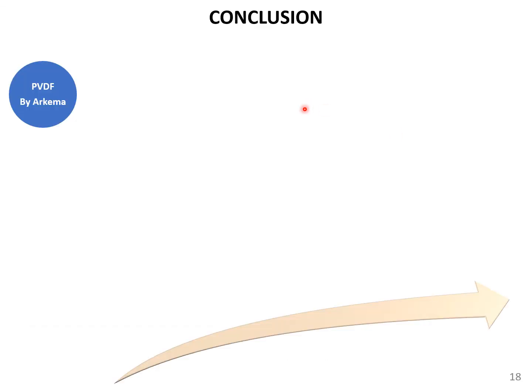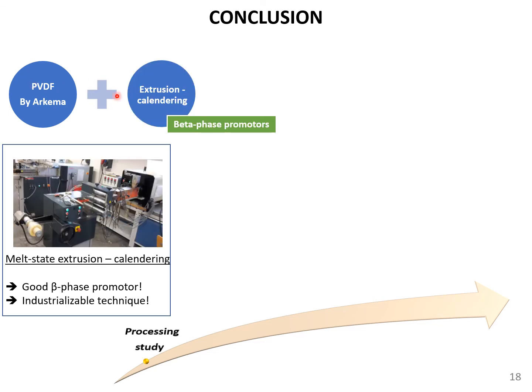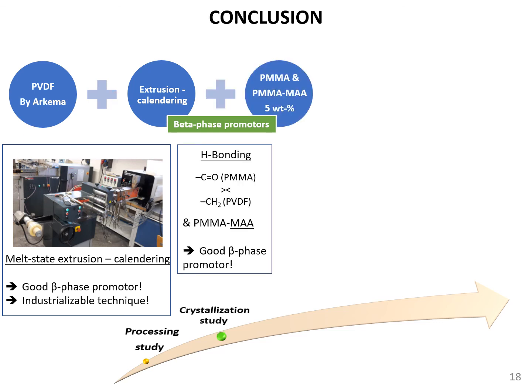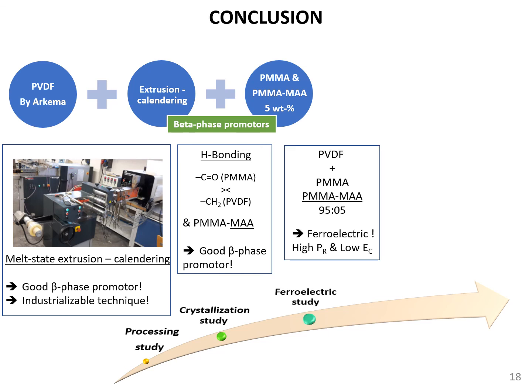As a conclusion, starting from a commercial grade of PVDF as provided by Arkema, and by applying an extrusion calendering process in order to promote the beta phase, we were able to achieve such results by the fact that you have positive or additional hydrogen bonding that can promote the beta phase as shown by crystallization investigation.